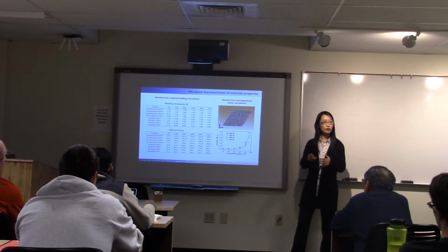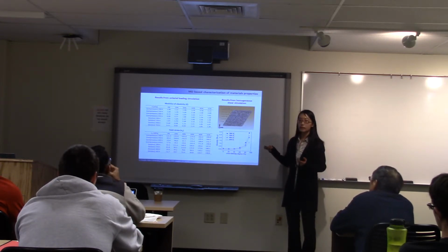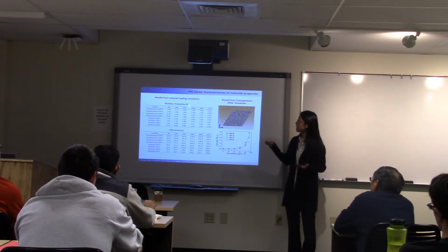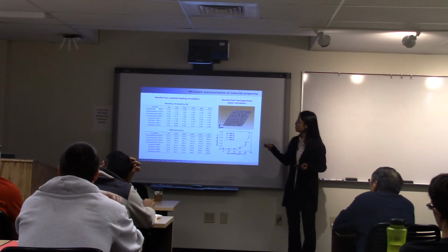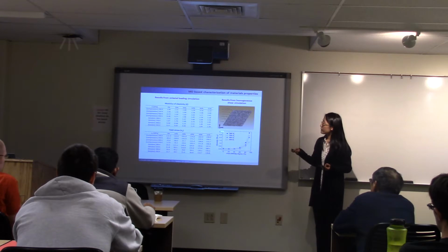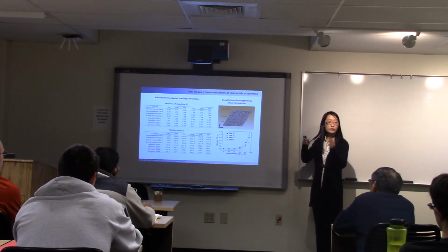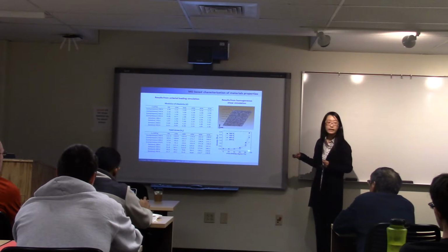We further did some uniaxial loading simulations, which are similar to the one I previously showed, and extracted some important mechanical properties such as the elastic modulus for both compression and tension at various temperatures, as well as the yield stress. Then the viscosity we obtained from the homogeneous shear simulation. This gives the model, also called the Cross model, and the viscosity at various temperatures for different cross-linking degrees is obtained here.